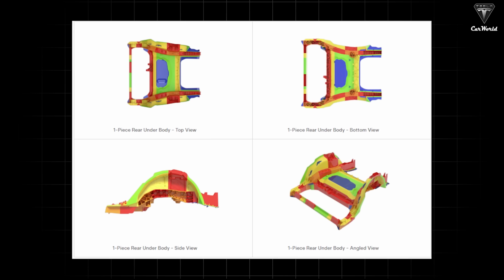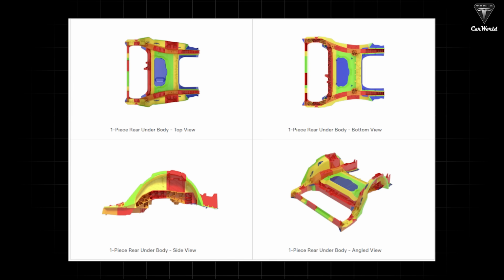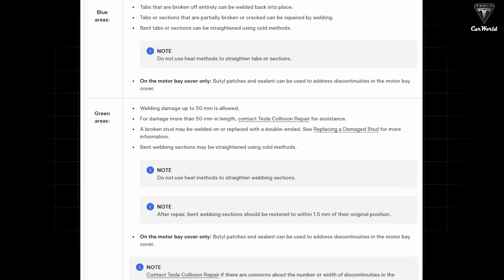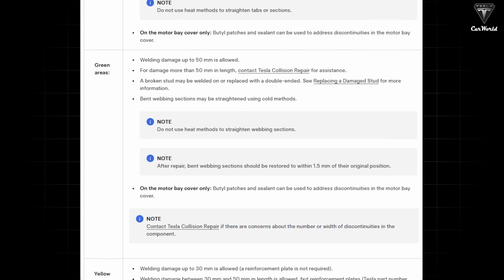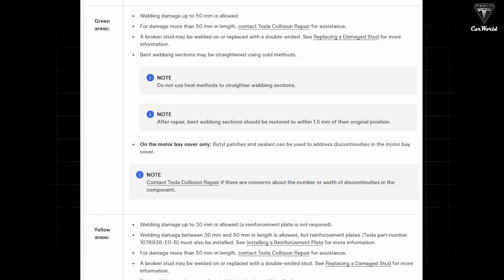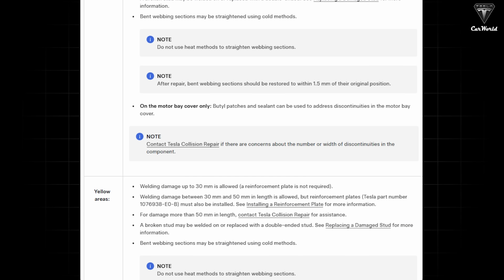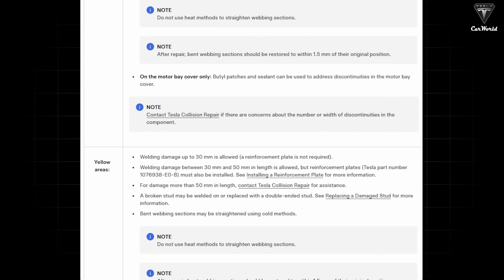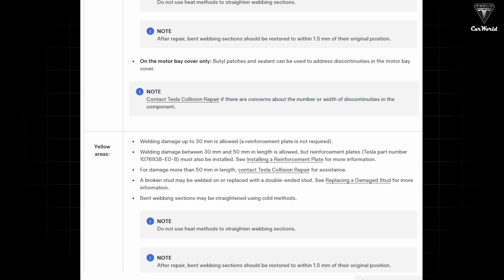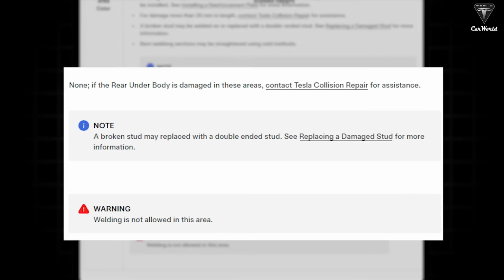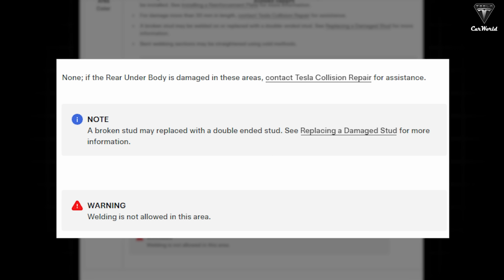Tesla now provides dedicated repair procedures for the Model Y's rear mega casting. In many areas, Tesla allows technicians to cold straighten bent sections, weld small cracks, reinforce damaged areas with reinforcement plates, and even replace individual sections of the rear rail instead of replacing the entire casting. Only when the damage affects critical areas or exceeds certain limits does the entire casting assembly need to be replaced.